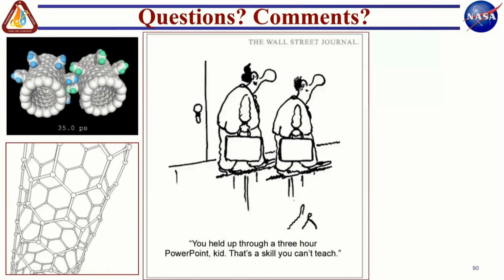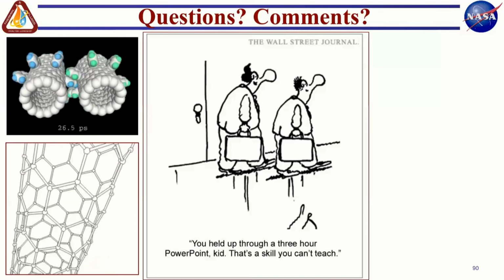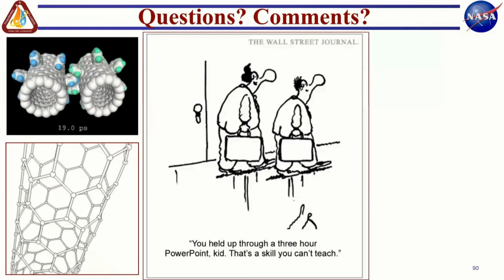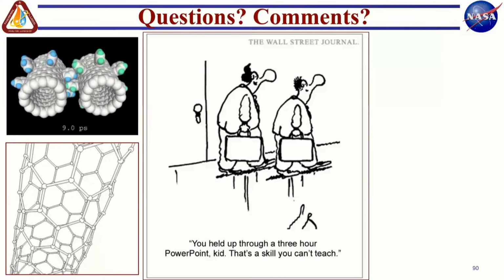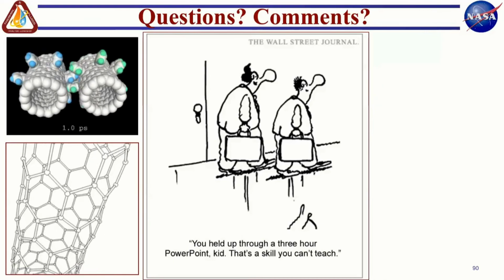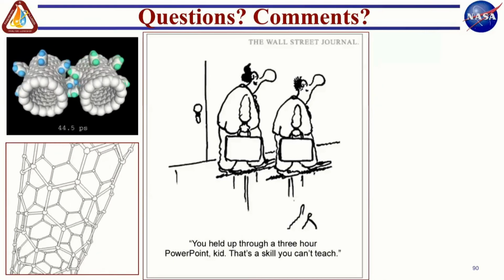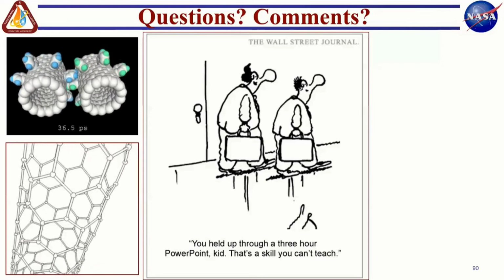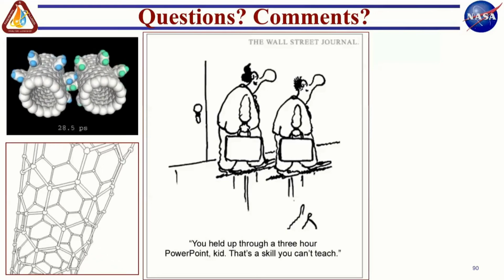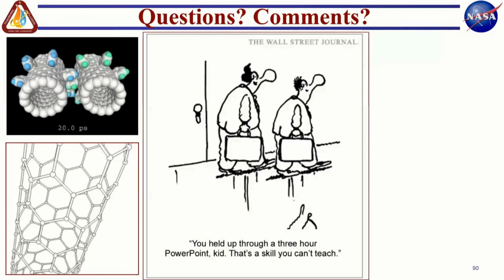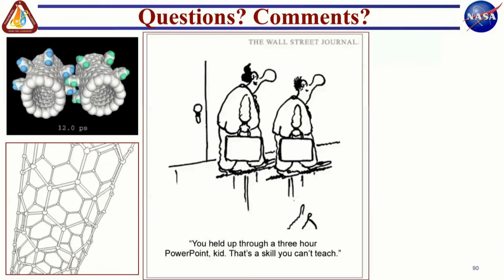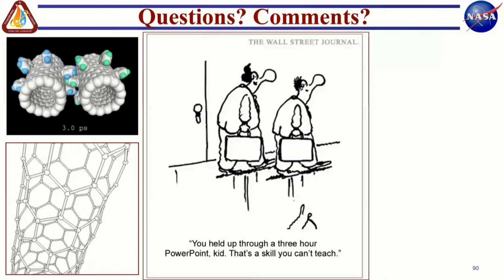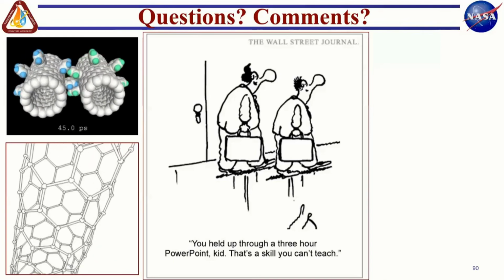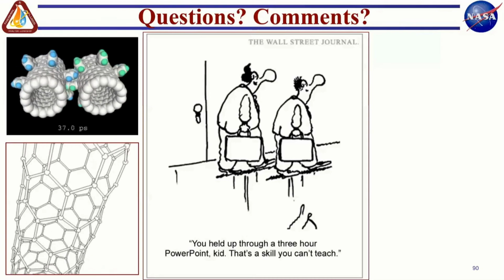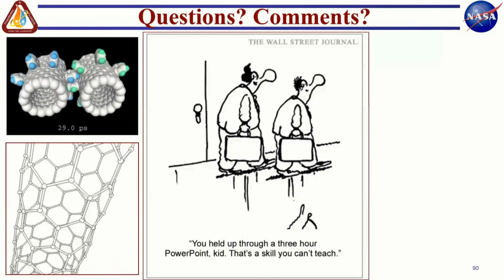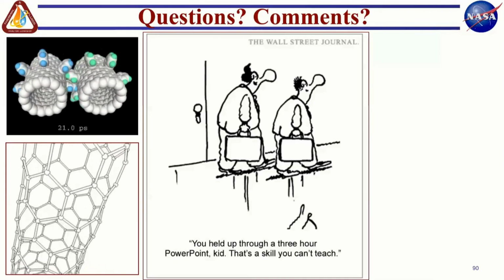And I didn't want to get into a garbage in, garbage out situation. So I didn't want to dabble in something that I don't understand. So I consciously stayed out of water because I have no idea which particular model of water to use, given our configuration here. On the other hand, molten salts are less controversial in the molecular dynamics literature. So we decided to do this for molten salts and organic molecules like alcohol, acetone, polyalpha olefin, hydrocarbons, and so on, because those are much more tractable in an MD simulation architecture. So that's where we did these predictions and measurements.